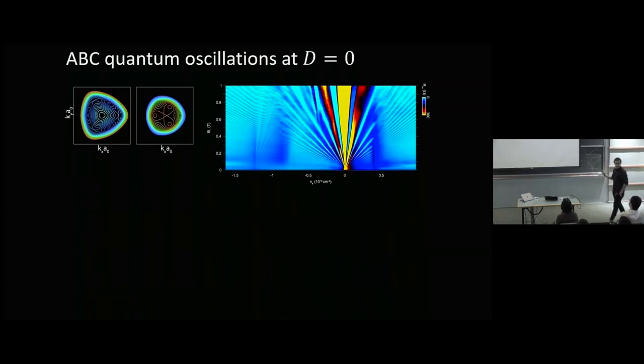which is not something that's true of twisted bilayer and related structures. So to give you an example of one of the tools that's really useful in our toolbox, this is a map of magnetoresistance of rhombohedral trilayer graphene. And I want you to notice the Y scale. This is from 0 to 1 Tesla. And you have tons of quantum oscillations really in the very low field limit because these are very clean samples.